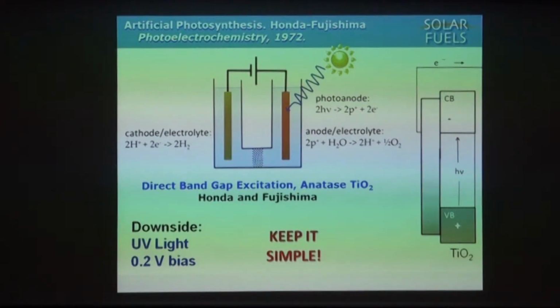And what they showed was that you could take TiO₂, and if you shine light on TiO₂ and connect it in a circuit with a platinum electrode, there is net current flow. The TiO₂ absorbs high-energy photons. That releases electrons that go to a platinum electrode where protons are reduced to hydrogen. The key to this at the photoelectrode is so-called band gap excitation.